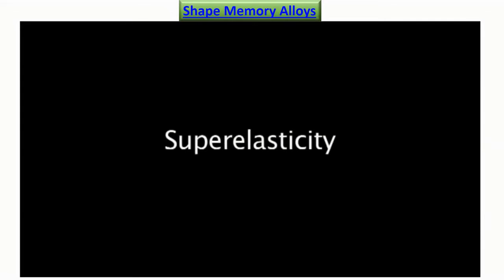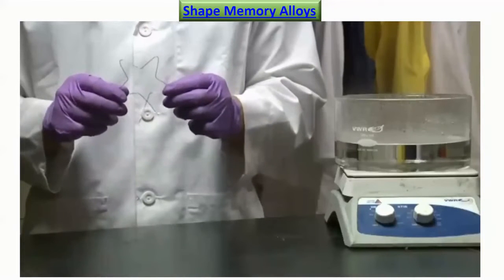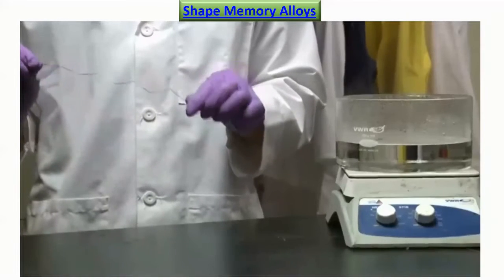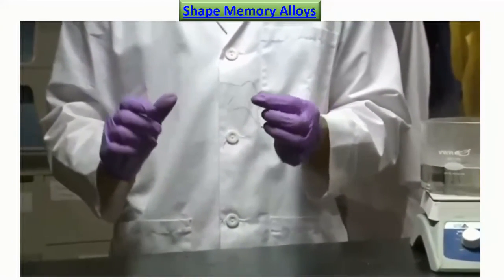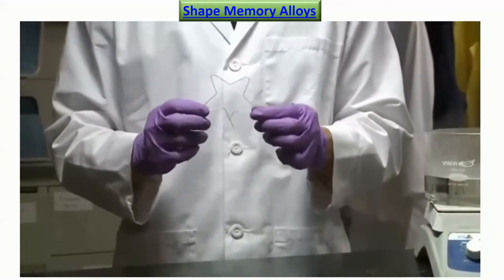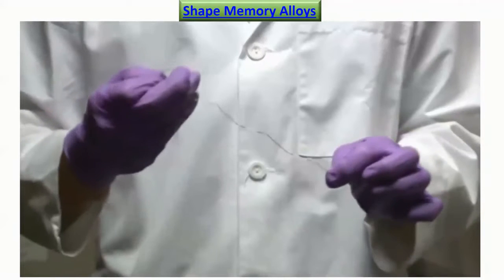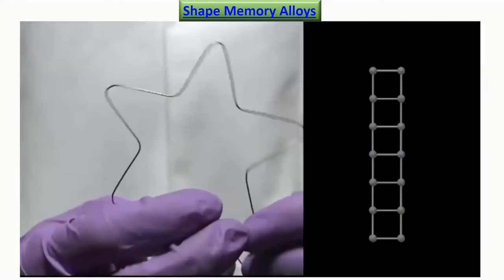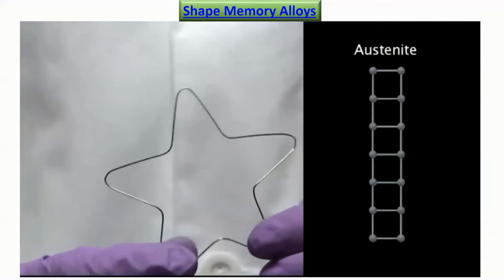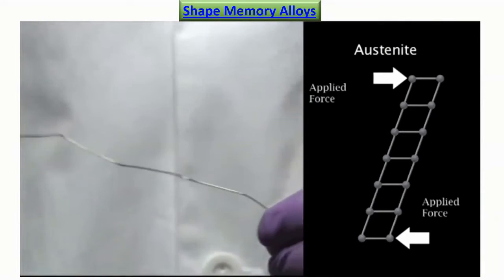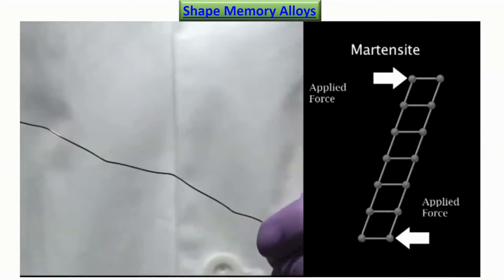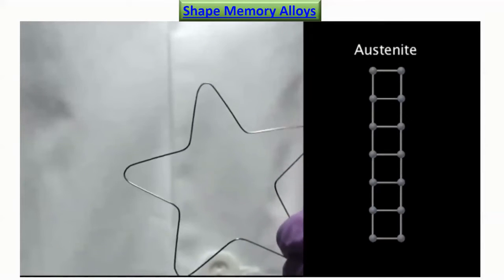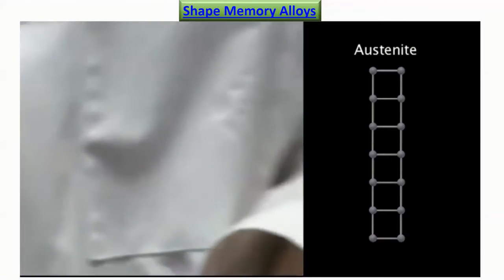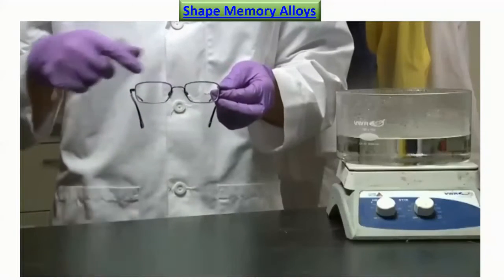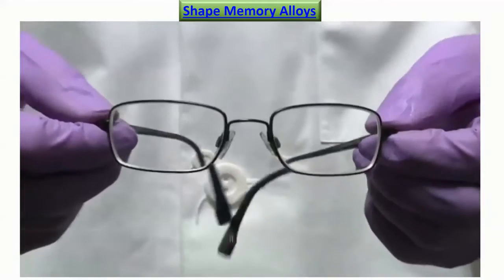Shape memory materials also exhibit another special property called superelasticity. Here's the same shape we saw before, and now we will pull it. But unlike before, this time the shape doesn't change, but it goes right back to its original shape. This is called superelasticity. This also works because of phase transformations. This material is a slightly different composition, so that at room temperature, it is in the austenite phase. If we stress the material, we can force it into the martensite phase, and this will change the shape. But if we release the stress, it goes right back to the austenite phase and the original shape because that is where it is stable at this temperature. You may have seen this before in eyeglasses that can be stretched without being permanently bent.